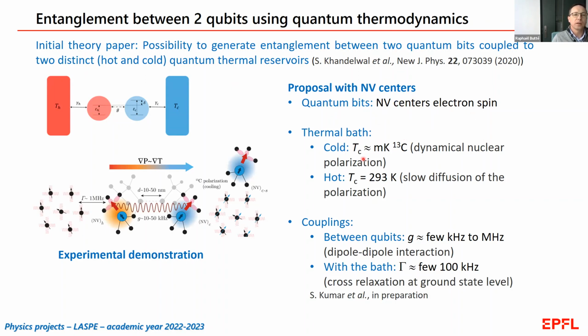Regarding the thermal bath, the cold bath would be the result of the dynamical nuclear polarization of carbon-13 atoms, which would exhibit an effective temperature on the order of a few millikelvins, while the hot bath would be at room temperature and would be the result of the slow diffusion process of the polarization.